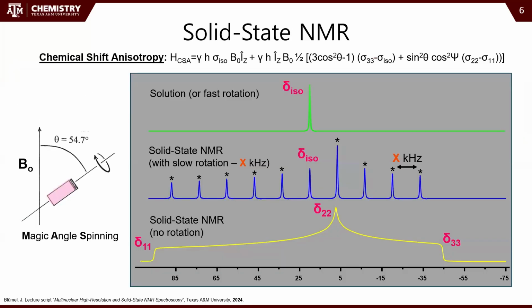So solid state NMR is dominated by chemical shift anisotropy. So that's this characteristic shape here, and that's defined by these delta 1,1, 2,2, and 3,3 peaks. So if you have a material, each of these peaks will be unique to that material. But this is a very broad signal.